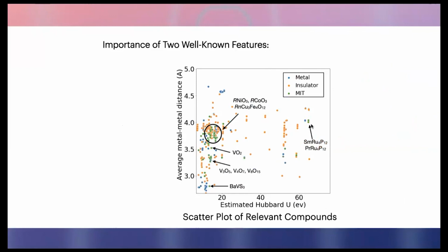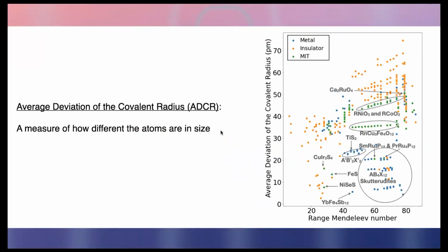And here you actually have quite a few covalent bonds, and ruthenium is actually D5. In our model, ruthenium ends up D0. So that is one of the difficult things with machine learning, is once you go outside of, say, a particular type of material, how do you featureize outside that in a way that makes some sense, right? Ruthenium here at D0, of course, would have 60 eV or something Hubbard U, but it's actually D5.